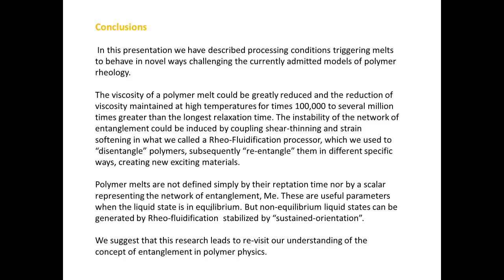But my conclusion is that non-equilibrium liquid states can be generated by rheofluidification, stabilized by sustained orientation. In other words, I can stabilize the melt in another new way by use of mechanical deformation in a nonlinear viscoelastic regime, which creates non-equilibrium liquid states. We suggest by this research that we need to revisit our understanding of the concept of entanglement in polymer physics.